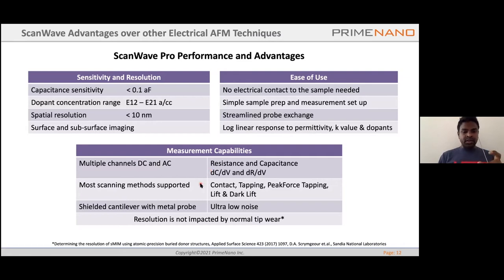The other important factor is the ScanWave is compatible with most scanning methods, in the sense that you can do it in contact mode, where the signal strength is much stronger because of the proximity to the sample. But you can also do it in tapping slash AC mode, wherein you oscillate at the resonant frequency of the cantilever. You can also do it in other modes, such as peak force tapping. You can use all the other bells and whistles which come with an AFM system, and you still can get the resolution and the sensitivity that we're talking about.